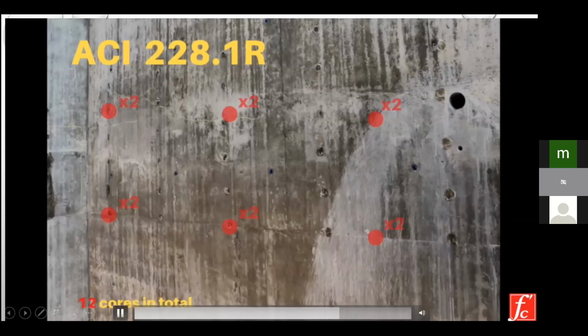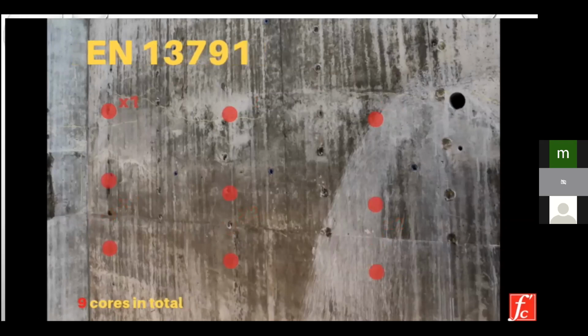According to the ACI 228.1R, in order to establish a relationship between the rebound number and the concrete strength, inspectors should take a minimum of 2 replicate cores from 6 or more locations. According to the EN 13791, 1 core should be taken from 9 different locations.